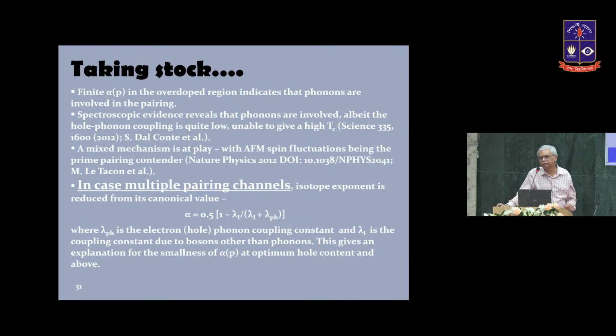So what will be the implication? The implication is this, that phonons actually contribute to superconductivity. But that contribution is very much lower than what you expect from ordinary BCS-like superconductors. The isotope effect we get in the overdoped region, which I would say is the intrinsic isotope effect, not related with spin and charge density wave order, is something like 0.1 or even 0.05. In a canonical system, the isotope exponent is 0.5, so 5 to 10 times lower. So this is partly responsible for Cooper pairing, but the contribution is small.